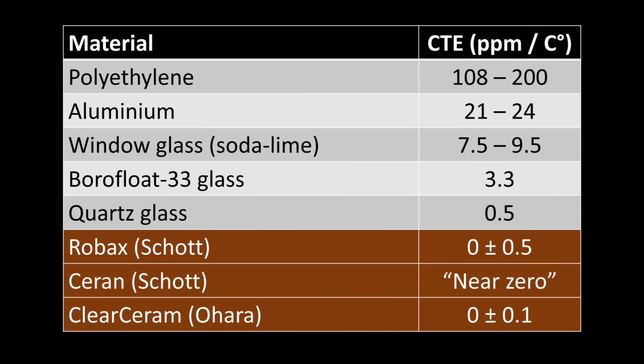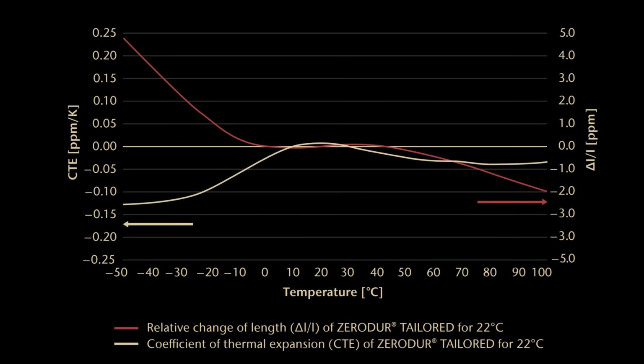So apparently the value can also vary between different batches. The CTE of Robax is specified as 0 plus or minus 0.5 ppm, and for Ceran it's actually not even specified, other than that it's near 0. And for Clearceram, a glass ceramic specifically intended for high precision applications, the CTE is specified to be 0 plus or minus 0.1. But in fact, tolerances can be much tighter, especially within a specific temperature interval.